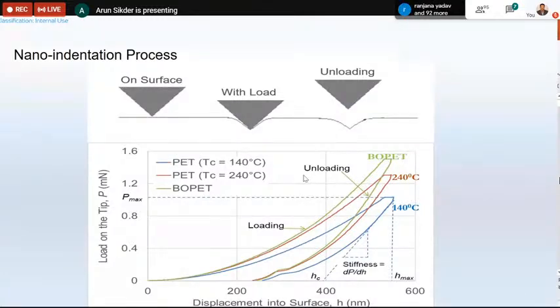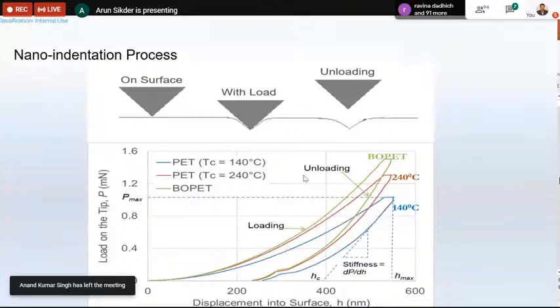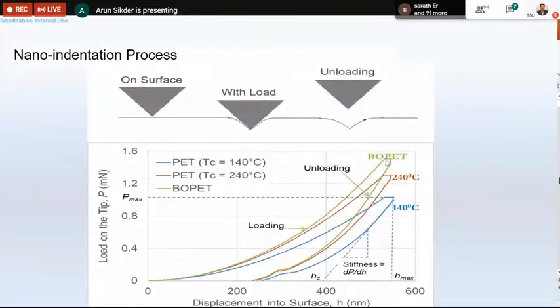What does it tell me, seeing this itself? It means the resistance to penetration of that tip was higher for BOPET samples compared to PET samples. With a lower load, PET has reached 500 nanometers. It takes a much higher load to reach 500 nanometers for BOPET. And in between is another sample. So it clearly says that the hardness of this BOPET will be higher compared to this. But how much, we will not know. We have to calculate that from the software, and then we know from the model. So that's it.